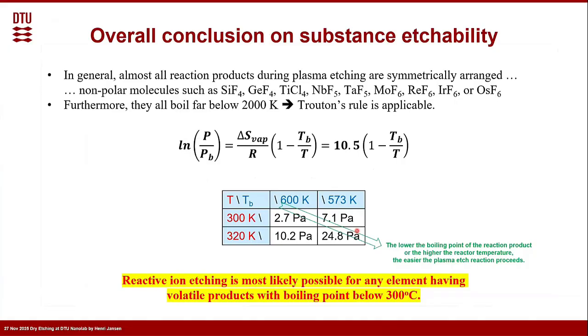But in general, almost all reaction products during plasma etching are symmetrically arranged. Those are the non-polar molecules like silicon tetrafluoride. It is a very symmetric molecule. Germanium tetrafluoride, titanium tetrachloride, niobium pentafluoride: they're all molecules where the atoms are arranged in such a way that they have a very symmetric and non-polar character. And all these kinds of compounds, products, typically boil off far below 2000 Kelvin. It means that in practically all cases we can apply Trouton's rule without thinking. So we are allowed to say that Trouton's rule applies for everything that is going to happen in our reactor when the products are volatile.